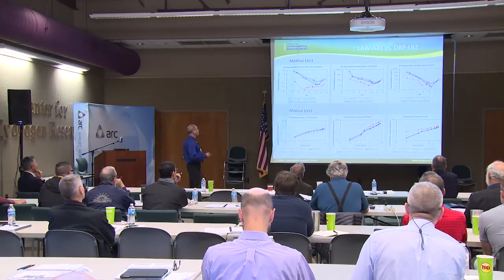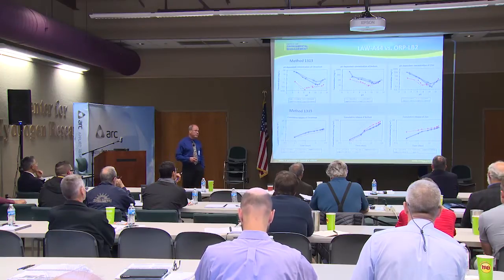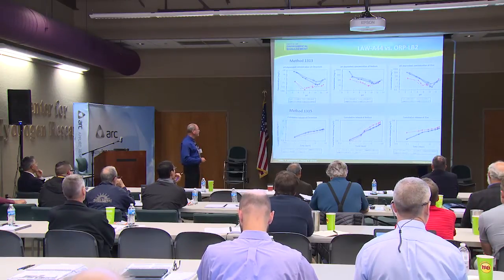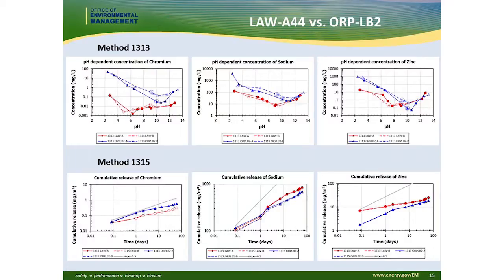So then the question is, well, could we distinguish different glasses? And these are just the same tests, the 1313, 1315, for these two glasses, which are different formulations, nominally not that widely different composition. And the answer was simply yes, we can distinguish the different glasses. We do see different responses to them. So it seems to be very sensitive to that as well. So both tests were both the 1313 and the 1315.